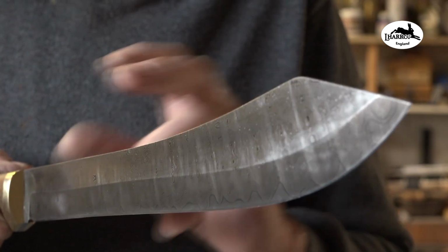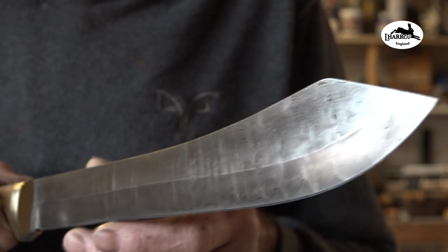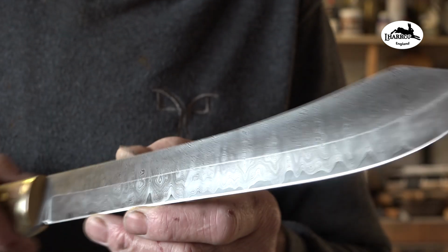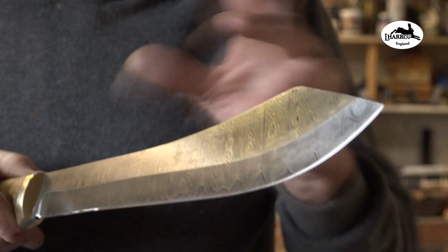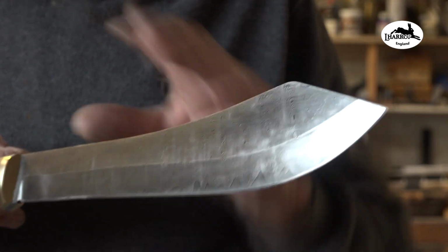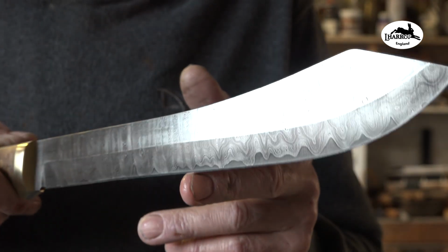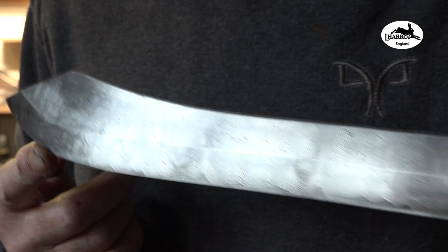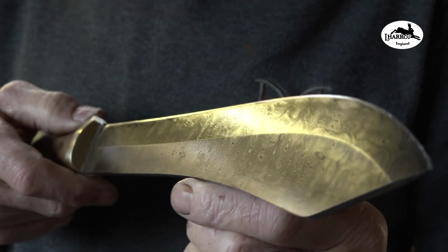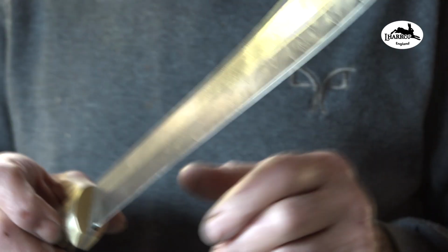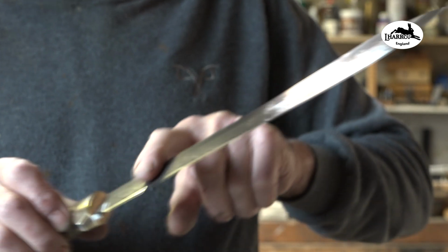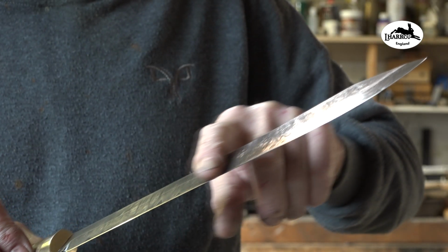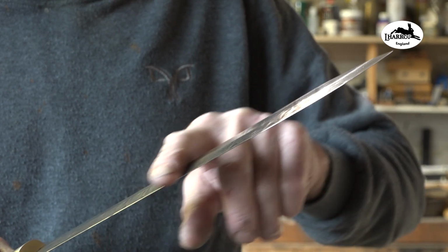weak acid etch to kind of just blacken off the 1095 and not really affect the nickel. The first acid I put it into was the stronger mixture. I just got them mixed up, so I etched too deep and messed up the nickel. Had to redo the flats and regrind the bevels, but we're there now. Both sides pretty much the same. See that chatoyancy? Better from that side, and the sunlight maybe just catches it. I didn't etch deep because I wanted to keep the finish as smooth as possible. So we've literally just got a very, very light etch on the 1095.